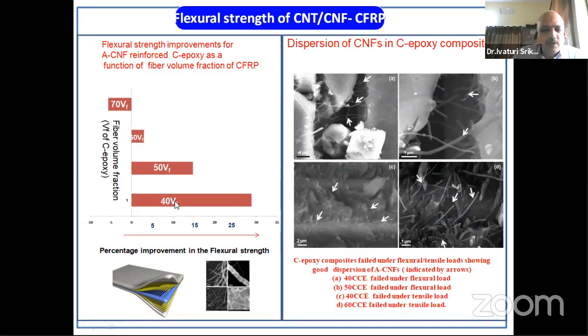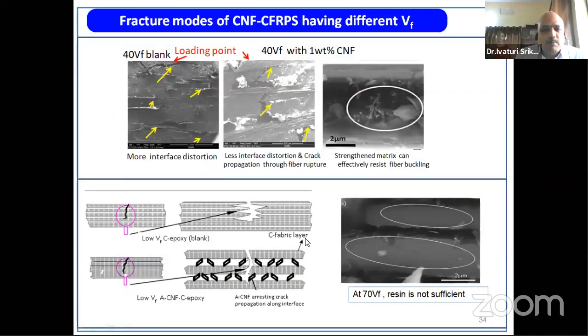to 30%. So your 500 MPa may become 600, 700, but with a conventional composite, conventional carbon fiber, you can anyway get it without even CNT if you make it with a high fiber volume fraction. If you try to add the CNTs in high fiber volume fraction composites, they will negatively affect it. So strength will come down. The reasons for this, we have systematically studied, and we have published also.